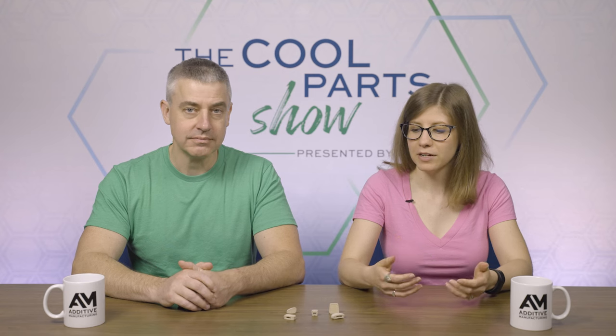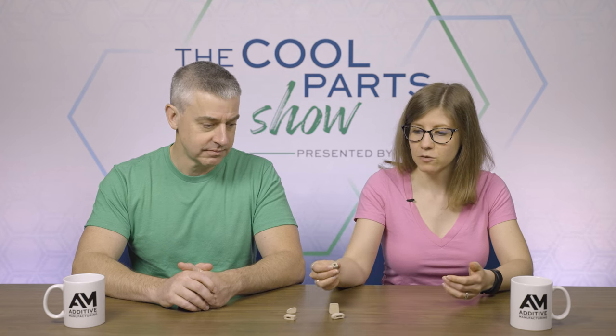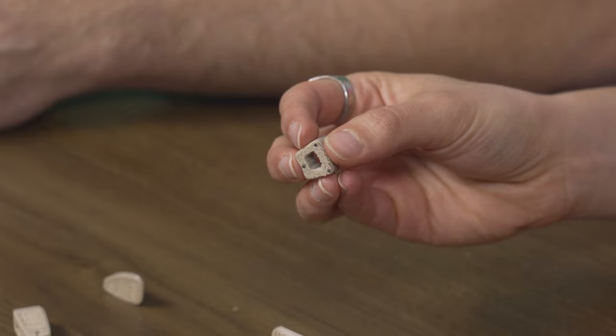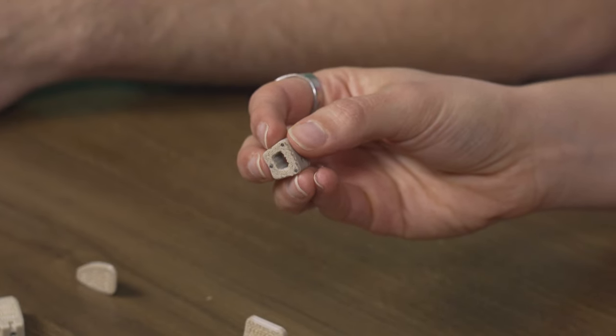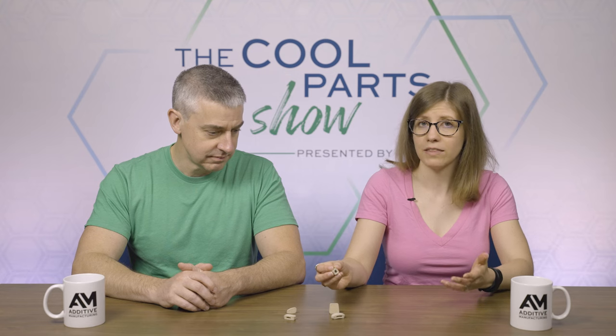And so we achieved a compressive strength 6 times what is required for physiologic loads and 2 to 4 times any implant that's on the market. It's indeed because of this 3D printing approach. So this printing process is a really good match for PEEK's material properties. And by 3D printing these implants one at a time, Curiteva can precisely control that thermal history. They can get the crystallinity and that compressive strength that they're after.